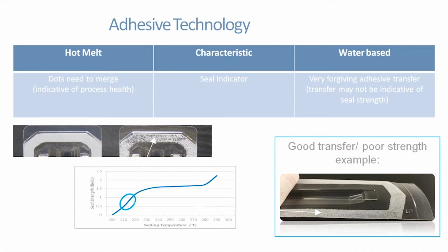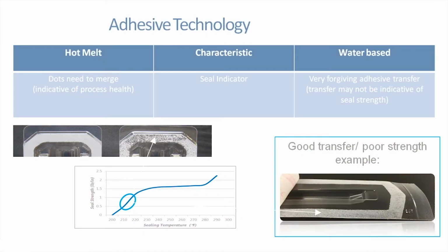So the seal indication, the adhesive transfer, that's another characteristic that's a little bit different. With the hot melt, think about the dots that we're applying. In your sealing processes, you have to get those dots to activate, flow, and merge together to get a continuous seal. With the water-based, you've got a flood coating, so you're not having to get dots to merge together to get a good adhesive transfer.